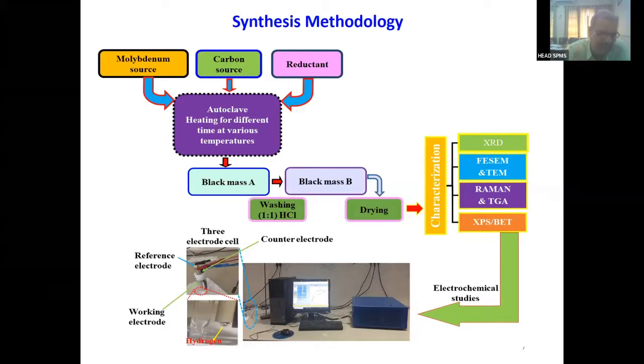So we hunted for different types of materials, and after a lot of hunting, we could come up with one class of material where the coefficient of thermal expansion is considerably low compared to different types of steels that we had taken. And the second thing is the gaskets, the choice of gaskets which are not going to break or burst even at such high temperature. All these things have been optimized and fabricated many times, and after a lot of failure, we could succeed in designing this autoclave.